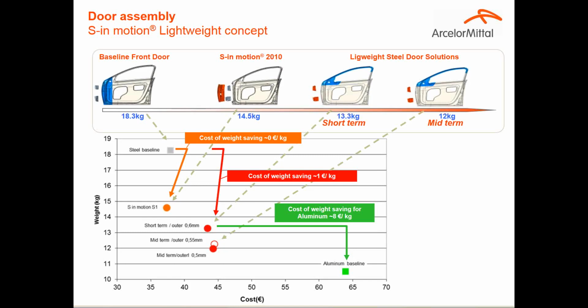What we did now, we applied new concepts of laser welded blank for the inner and new grades for the exposed panels, simplifying a bit the design of the patches in order to close this gap. And in part we succeeded. It's not easy to maintain the same thickness of the aluminum one, of course. But starting from 18 kilos in 2005, we are today close to 12, and not far from the target in aluminum.